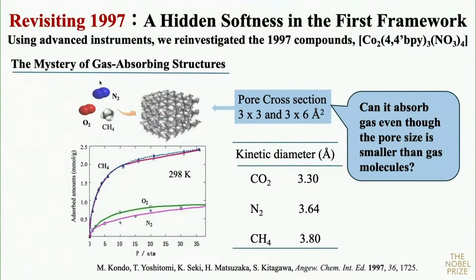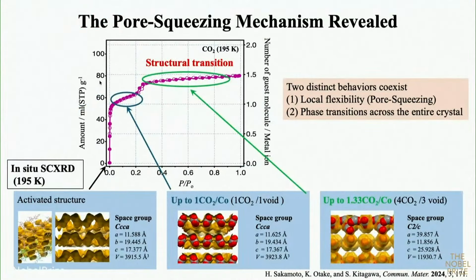So very recently, we had a big question, because in 1997, this is very important, our materials first demonstrated gas sorption. But without gas, in this structure, the pore size is smaller than the gas molecule. How is the gas molecule accommodated in this way? This is a big issue. So we revisited these materials, and this case is CO2. CO2 adsorbed smoothly at the lower pressure region. And what is interesting is that in the second step, abrupt adsorption occurs here.